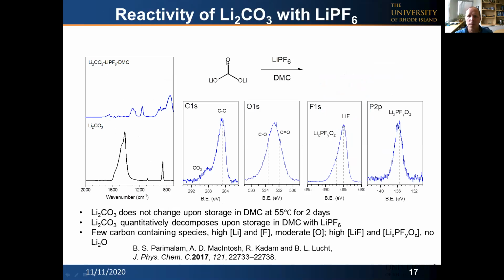So with that in mind, we wanted to go back and look and see how lithium carbonates react with LiPF6 in a standard dialkyl carbonate. So once again, in this case, we took lithium hexafluorophosphate, dissolved it in dimethyl carbonate, added it to lithium carbonate, and then stored the samples at moderately elevated temperatures, 55 degrees centigrade, for only 2 days. And what we observed, surprisingly, was that the lithium carbonate quantitatively decomposes over this time frame. We start off the IR spectrum of lithium carbonate, and then after 2 days, there's no lithium carbonate present whatsoever.